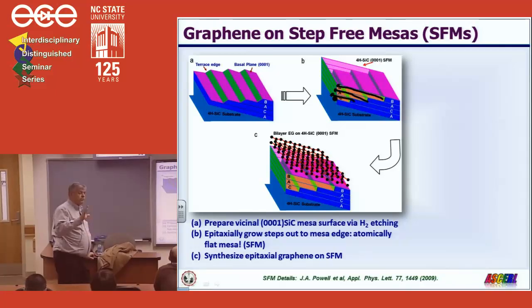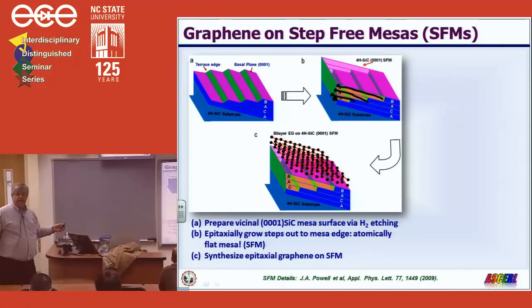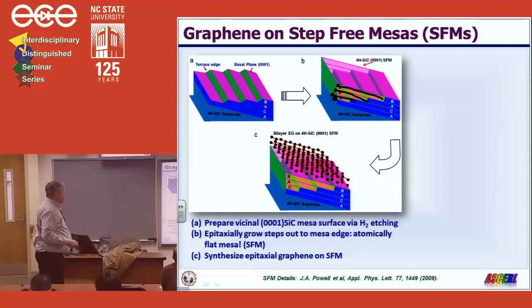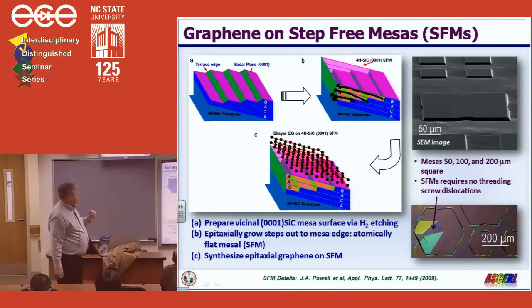And what I've done is I've changed the growth conditions in a very careful way so the growth will automatically shut off once all the steps are gone. Now I have a flat mesa, and I subject it to the same graphene growth conditions that I did before, and that's depicted in the ball and stick model in the lower portion of the figure. And this is what a graphene covered mesa looks like.